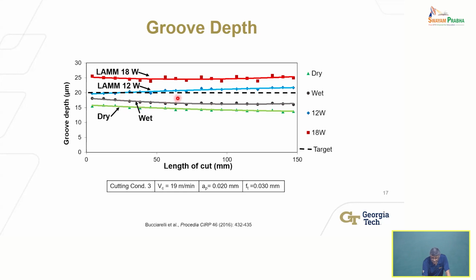With 12 watts, the dashed line is the target, nominal. Depending on the initial portion of the cut, this is length of cut, in the initial portion of the cut, it's actually pretty good, close to 20, right? Or at 20 almost. But then it starts to deviate. Why does it deviate? And the deviation increases at higher laser wattage. Why? What do you think?